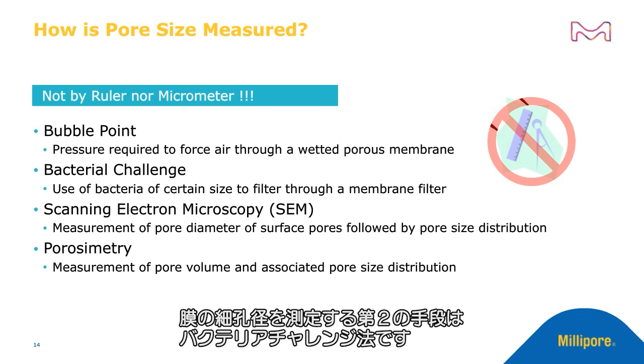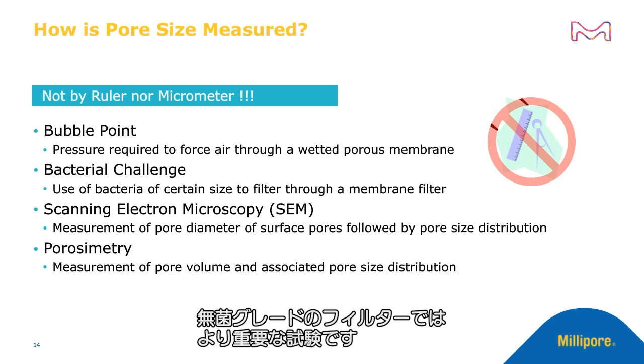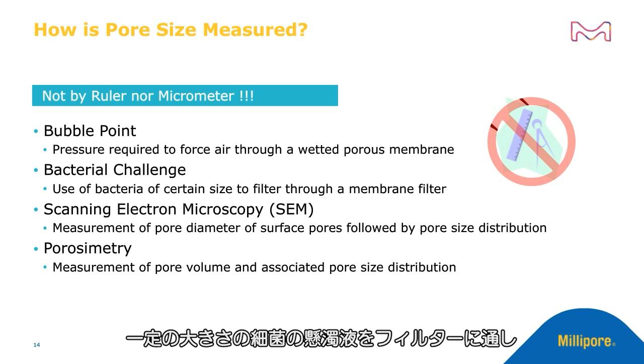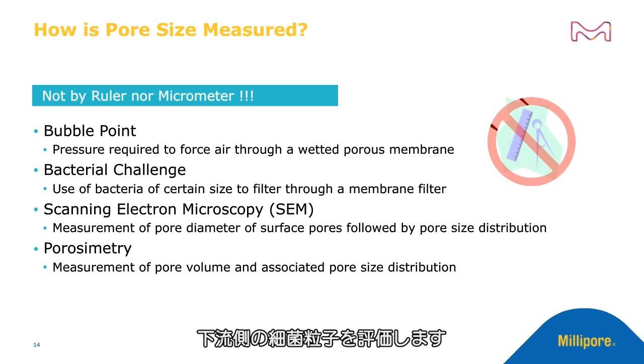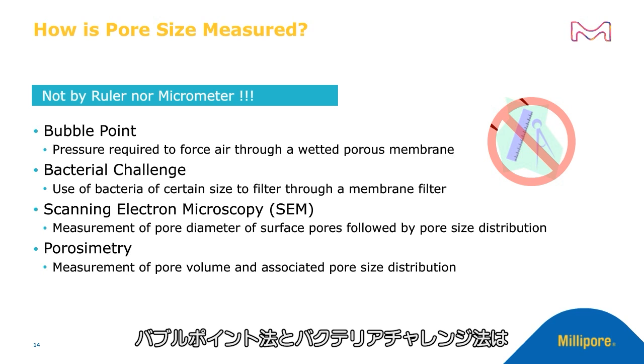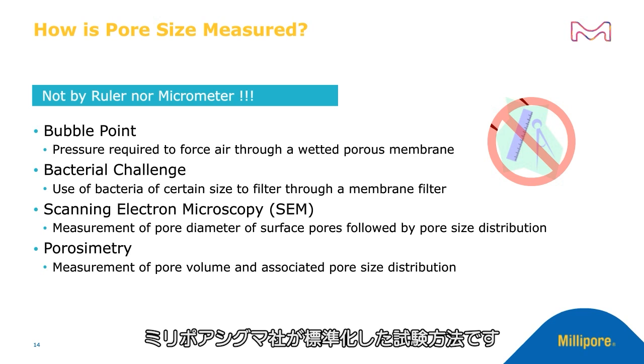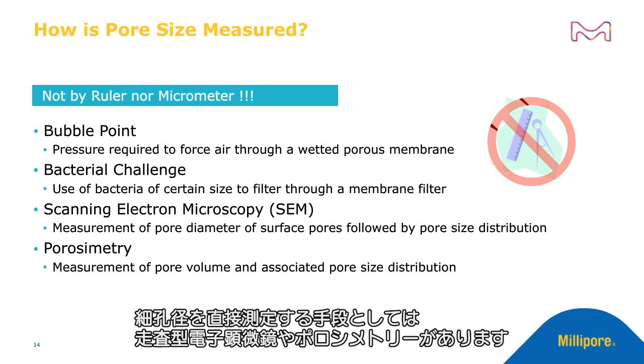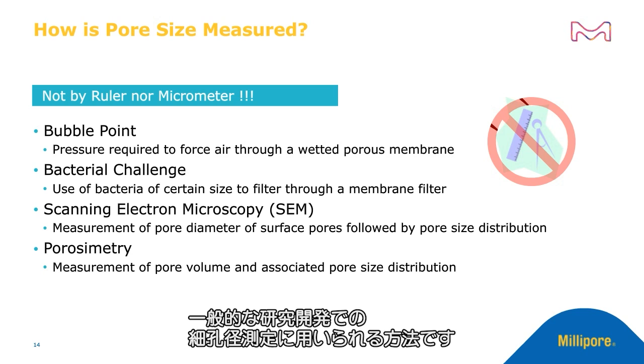The second means for measuring pore size of a membrane is by bacterial challenge. This test is more important for sterile grade filters, where a bacterial suspension of certain size bacteria is allowed to pass through a filter and the bacterial particles on the downstream side are evaluated. Both the bubble point and bacterial challenge are test methods which have been standardized for a number of years by MilliporeSigma. But both of these are indirect methods of measuring pore sizes. Some of the direct methods of measuring pore size are scanning electron microscopy and porosimetry. But these are generally used in R&D for pore size measurement.